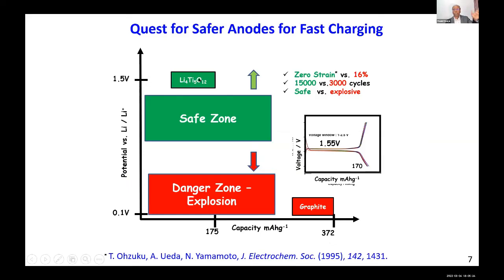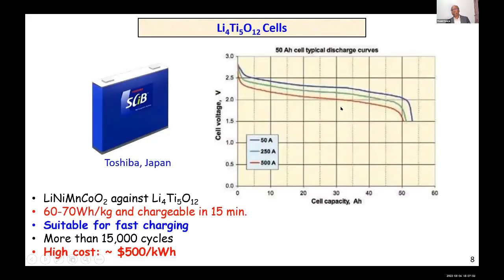The insertion potential and extraction potential in lithium titanate is about 1.5 volt, far away from the 0 potential, which is the lithium reference, whereas graphite operates at 0.2 volt, as I told you. So this is unsafe, whereas this is safe when it comes to quick charging, quick discharging. I can do it in 15 minutes charging. I can discharge it in 15 minutes. Incidentally, this material has 0 strain, so a large number of cycles can be covered, and it is extremely safe. You can see here, Toshiba has commercialized that.